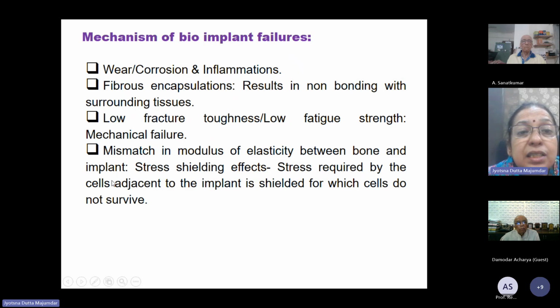So what are the reasons? The reasons are wear, corrosion and inflammation, fibrous encapsulation, low fracture toughness, low fatigue strength, mechanical failure, and mismatch in the modulus of elasticity between the bone and implant, leading to the stress shielding effect. As a result, there is shielding of stress surrounding the implant material, leading to damage of the cells surrounding it, as a result of which cells cannot survive.